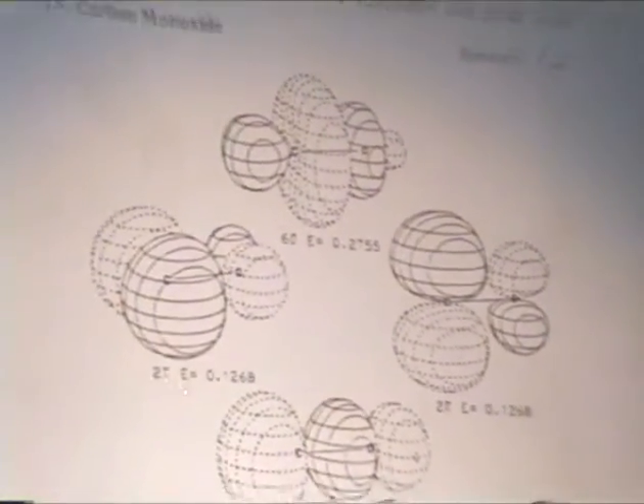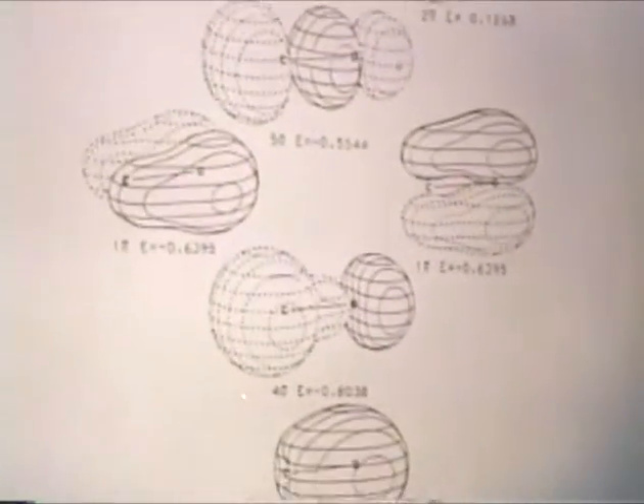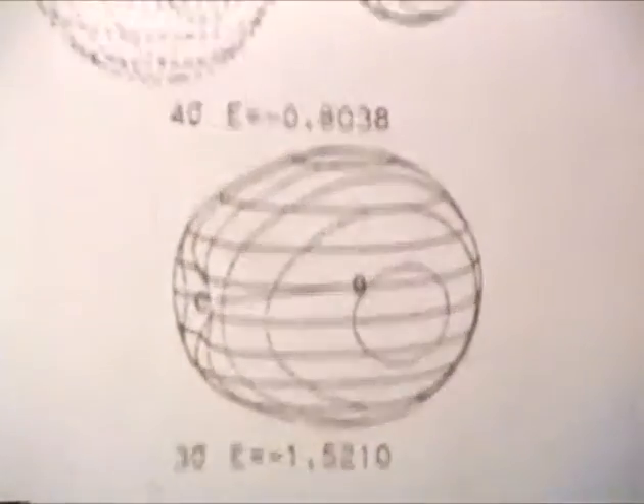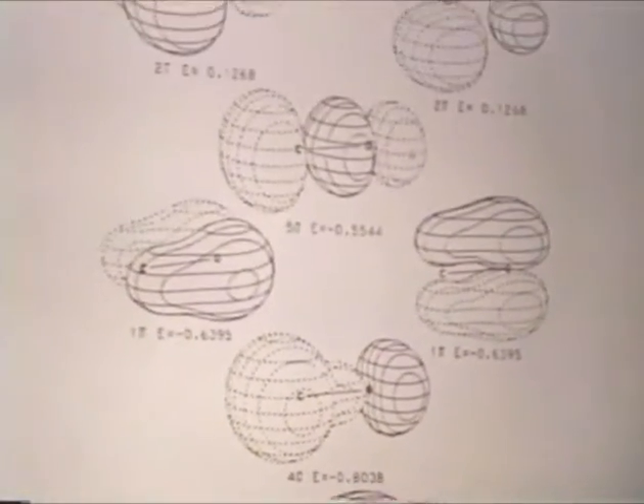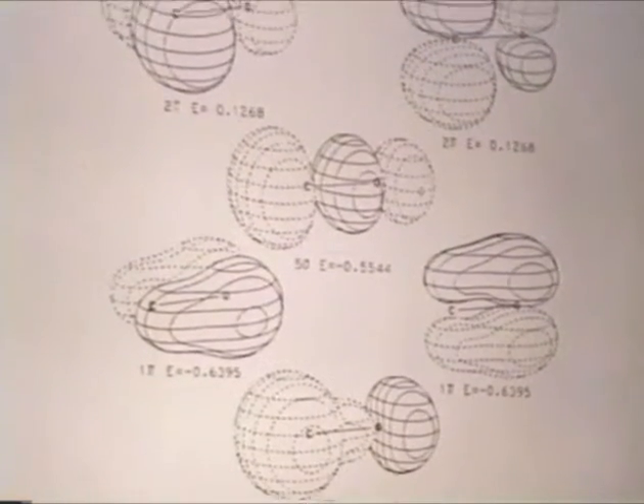Now that we've established that we have second order desorption, the next step was to look at some UPS. And just as a refresher for everyone, this is an illustration of the electron densities in the molecular orbitals of CO. The 5 sigma is the highest occupied molecular orbital. The 2 pi is the lowest unoccupied molecular orbital. The 1 pi and the 4 sigma are the next lowest molecular orbitals underneath the 5 sigma. And the 5 sigma is typically thought of as a non-bonding orbital because the electron density is centered so much around the carbon. So with that in mind, we did a UPS experiment